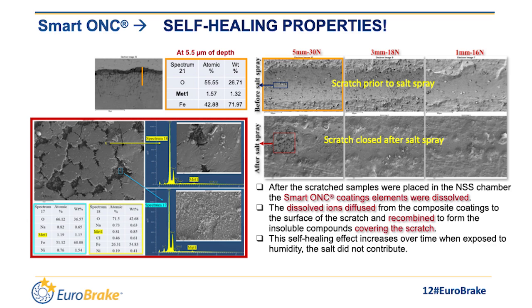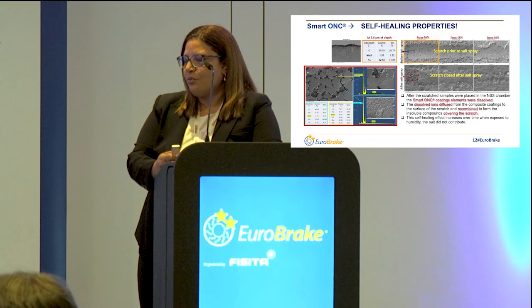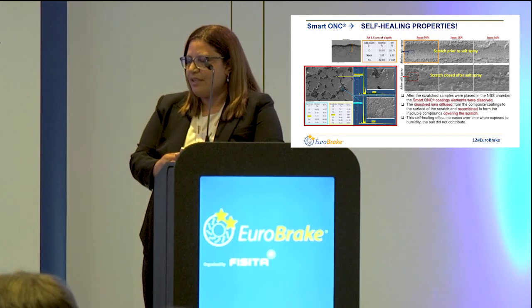performance. We also tracked the behavior of the Smart ONC scratched sample in salt spray, before and after. We can see that after scratching the sample and prior to putting it in salt spray, the deepest area at 5.5 microns shows the presence of oxygen and metal 1. After several hours of exposure, the scratch was almost completely covered. The deepest area in the red box is still under the self-healing process, which was shown by high magnification SEM on the left-hand side and confirmed by chemical composition, which shows that we have metal 1 oxide and we note the absence of nitrogen and carbon.